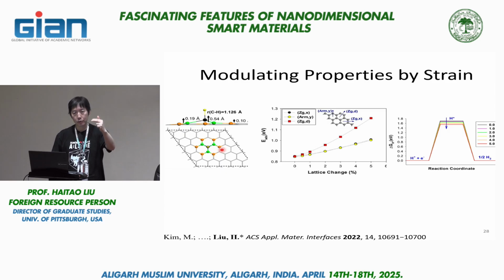And a stronger absorption would essentially lower the activation barrier. But you can't make it too low. If you make it too low, then you are trapped with the intermediate. So what we're doing here is essentially we're modulating the absorption energy as a function of the lattice parameter. When we bend the graphene, we're essentially changing the carbon-carbon bond. And you may imagine that if I weaken the carbon-carbon bond, it makes it easier to absorb the hydrogen atom.